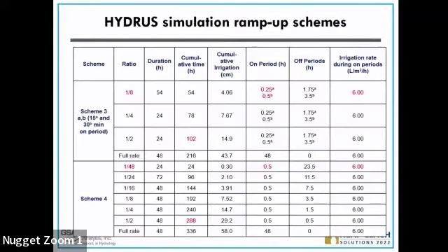And scheme 3, even faster. This one takes about four days to complete with the same flow rate. And so we also varied between the 0.25 and the 0.5 hours. The purpose of that is because, like I mentioned, the on-off actually helps the spreading of solution. And then we want to keep the loading as small as possible to even out solution distribution.